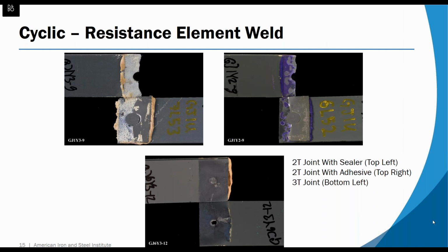The cyclic loading is actually relatively similar, but again, seeing a little bit more of a brittle mode. We are actually seeing a failure at the interface of the joining element in the two thickness joint, similarly in the two thickness with adhesive joint, and we are actually pulling a nugget out of the bottom sheet in the three thickness.